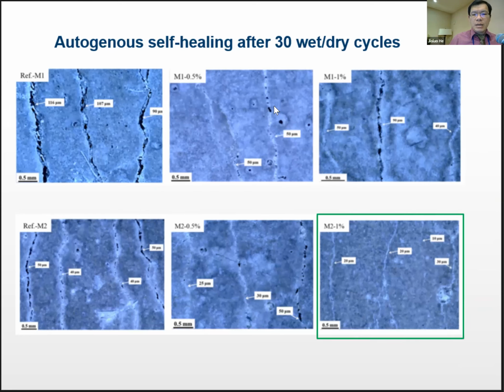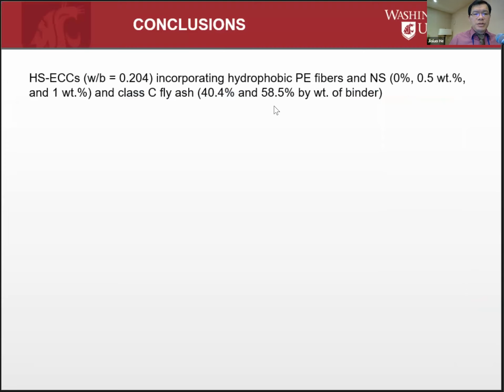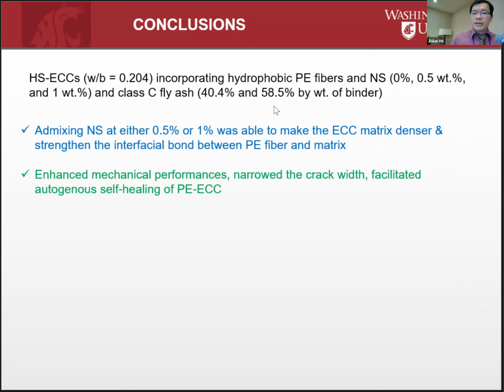And to conclude, basically we're achieving a high strength ECC with, sometimes even, high volume fly ash concrete. And they were able to make the matrix denser and improve the bond. And one thing I should mention is that in addition to enhancing the mechanical performance, you also have more cracks, narrow cracks, and better self-healing behavior.